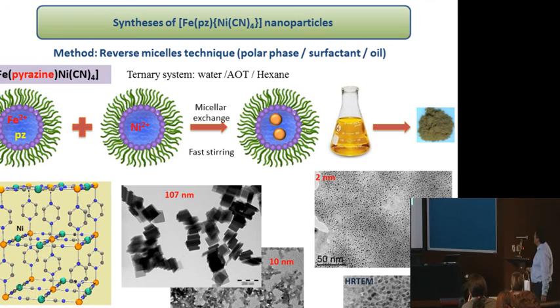Okay, this is what we did. We have seen already this slide. So we prepare two independent microemulsions, one containing pyrazine and iron, and the other the nickel, for example. After a micellar exchange and fast stirring, we grow the nanoparticles inside the micelles, and the growth is limited, of course, by the size of the micelles. So we obtain these types of microemulsions, and using centrifugation or evaporation, it's possible to obtain powder containing spin crossover nanoparticles. So modifying the concentration, we can have different sizes from, for example, 100 nanometers to 2 nanometers.